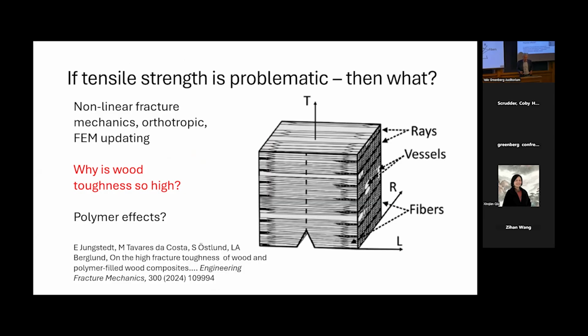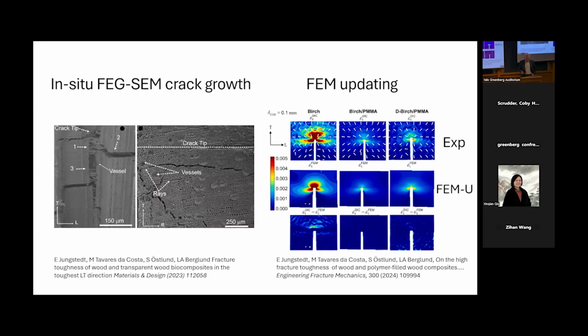I complained about tensile strength as a concept, so what can we use instead? When you design large structures, fracture mechanics is very helpful. I wanted to quickly present some methods, but also address the issue of why we perceive wood as such a tough material. On the left-hand side, you see microscopy studies of a crack growing in wood. The fibers are in the horizontal direction, and we're trying to grow the crack in the vertical direction here. But as you see, it deviates all the time. It tends to go to the sides here.